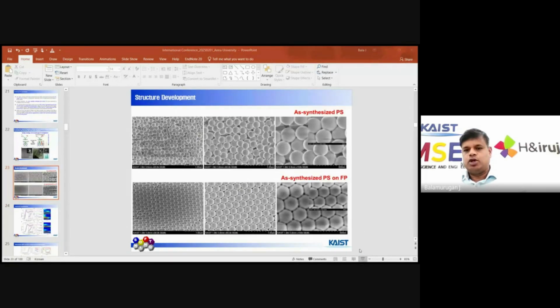For the basic media, I told you that we want to make porosity, therefore we make some PS molecules. You can see the homogeneous size of the PS molecules, and when dropped over the carbon paper, like a normal filter paper, you can see they perfectly make the pattern. This PS may be helpful to make high porosity in the graphitic carbon.